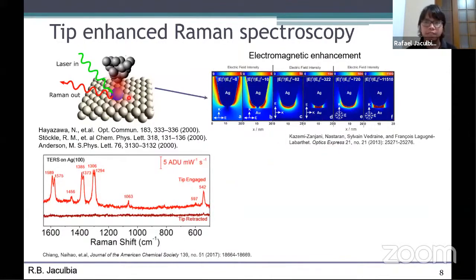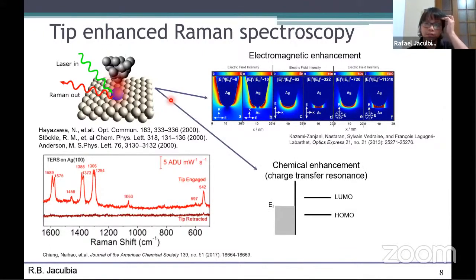This is the so-called electromagnetic enhancement, but there is also one more, the so-called chemical enhancement, more popularly known as charge transfer resonance, wherein instead of the direct excitation from the molecule's highest occupied orbital to the lowest unoccupied orbital, by placing the molecule near a metal, as is always done in TERS or SERS, you can get another source of electrons, charge transfer resonance in this case. So the Raman signal is enhanced in TERS because of these two effects, and these two effects happen simultaneously.